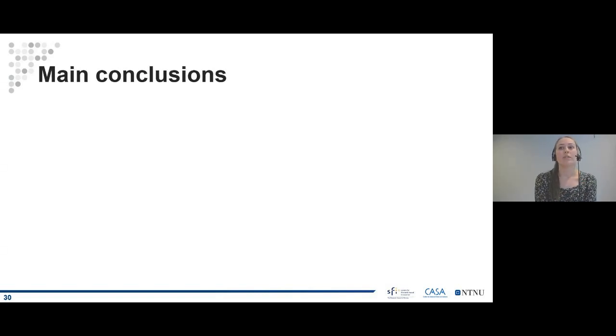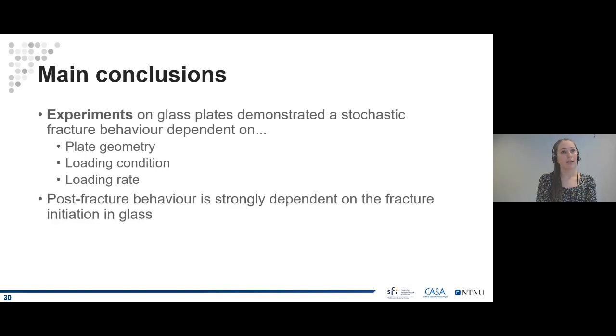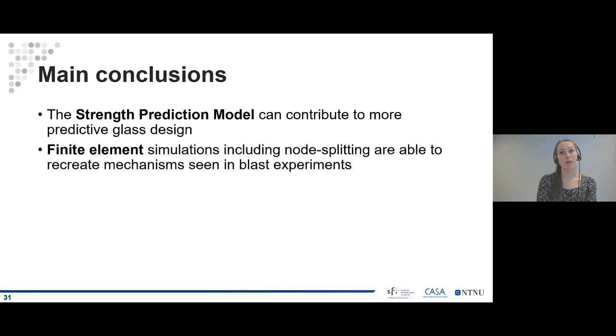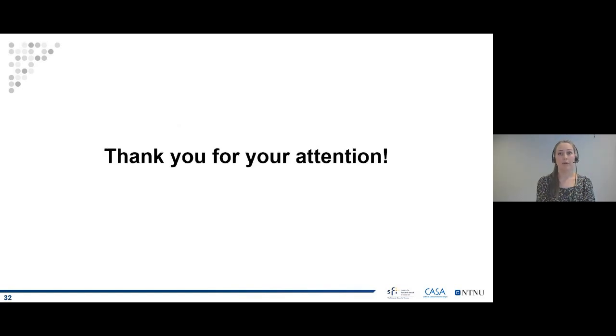Then over to the main conclusions of the PhD. The experiments that we performed demonstrated a stochastic fracture behavior that was dependent on the plate geometry, the loading conditions, and the loading rates. We also saw that the post-fracture behavior is very dependent on the fracture initiation in the glass. Also, we saw that the strength prediction model can contribute to more predictive glass design. And also that finite element simulations that use node splitting are able to recreate mechanisms that we saw in the blast experiments. Thank you very much for your attention.